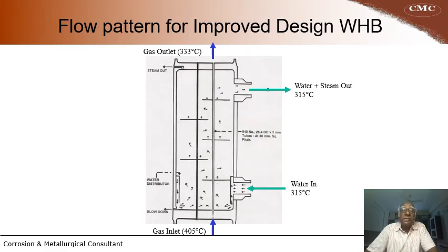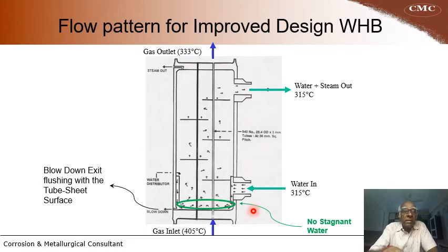So having seen the deficiency of the design, the recommended action was an improved design. On this improved design, you can notice at the bottom area, the blowdown drain is given flushing with the tube sheet surface. There is no stagnant water in the bottom area where the tubes have failed earlier. So this modification of removing the stagnant water has resulted in preventing the failure of the tubes. Blowdown exit flushing with the tube sheet surface. So there is no stagnant layer here.